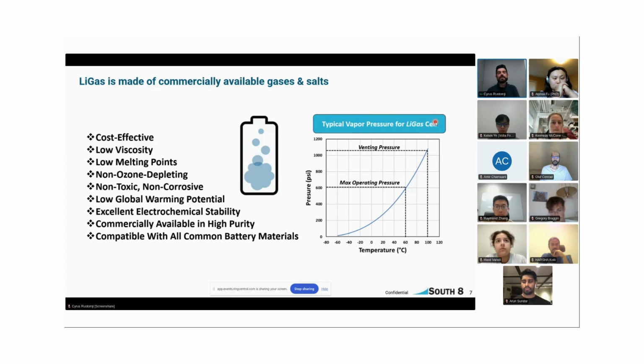We work with exclusively non-ozone depleting, non-toxic, and non-corrosive components. So anything acidic or that can be corrosive or toxic, we do not use. We do use some low global warming potential components, but these are significantly lower than your standard refrigerants. And so we are aiming to be very compliant with all the new regulations that are coming out. Of course, I already discussed electrochemical stability. We want these solvents to be very stable in your battery cell device to ensure long cycle life. And I already mentioned these are commercially available in high purity, and of course compatible with all your common battery materials. So we use all your standard anodes, cathodes, separators, binders, current collectors, all these items our gases are fully compatible with. So it's essentially a drop-in replacement for that jelly roll.